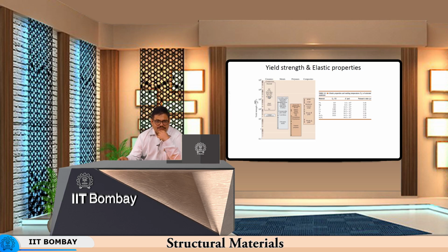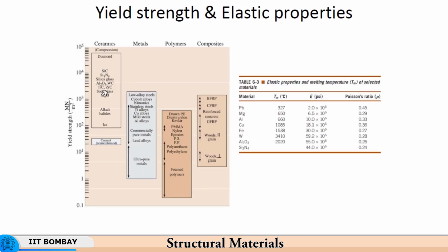You have polymers, which have completely different behavior with respect to loading compared to metals. You have metals in a wide range of yield strengths depending on how much you can alloy them, and therefore you can tailor the metals to different ranges, starting from 10 to the power 0 to 10 to the power 3 MPa, or something more than 10 to the power 3 MPa in yield strength.